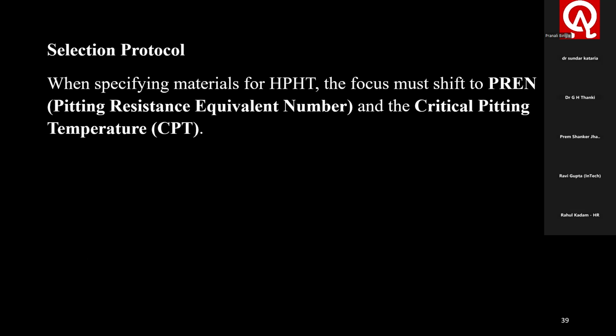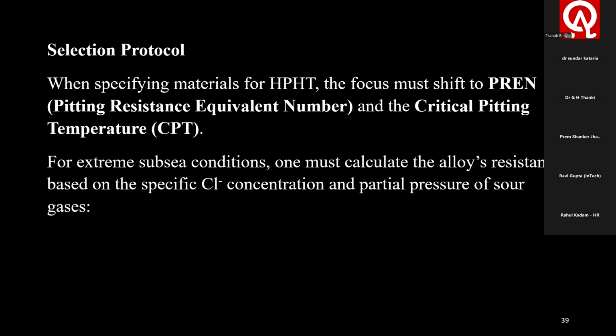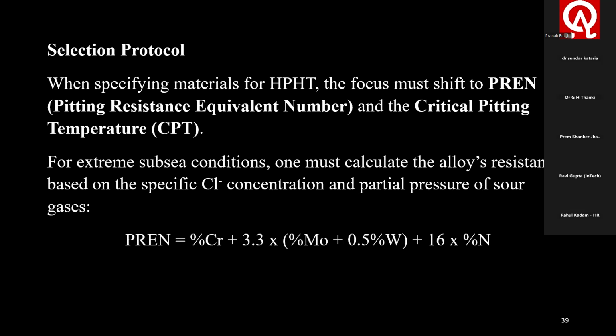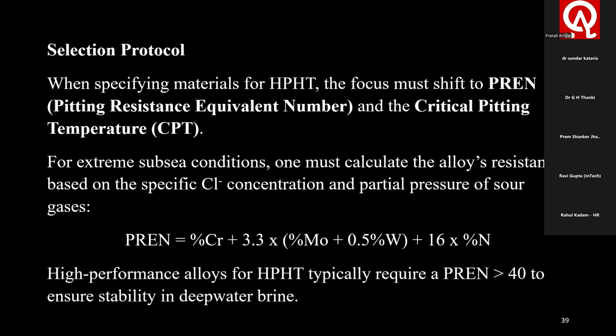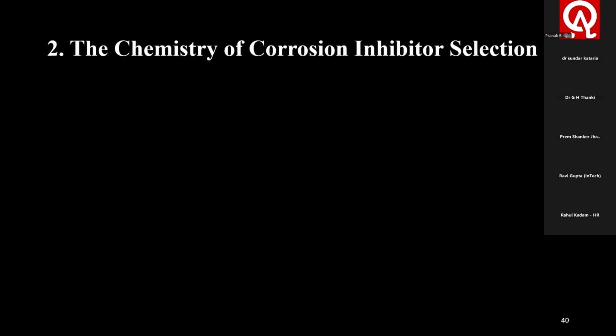Now, let us select the protocol. When specifying materials for HPHT, the focus must shift to pitting resistance equivalent number, that means PREN, and the critical pitting temperature, CPT. For example, in such conditions, one must calculate the alloy resistance based on the specific chloride concentration and partial pressure of sour gases. I am again referring back to that PREN equation. High performance alloys for HPHT typically require a PREN more than 40 to ensure stability in deep water brine.